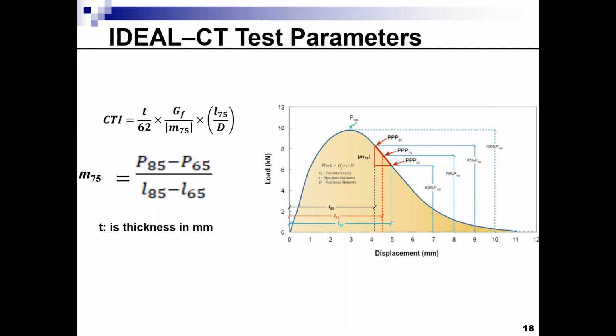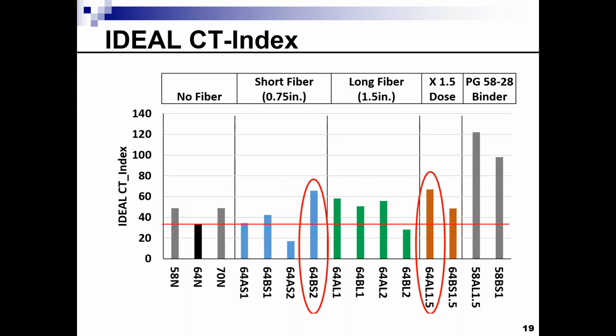We did the IDEAL-CT, and the main parameter there was the CTindex, which I'm showing here. Again, it is based on the fracture energy and also the slope of the post-peak, but there is a different way of getting the post-peak slope, as you can see. You can get it from this equation. So the IDEAL-CT, or CTindex, is another cracking index that has been proposed to evaluate the cracking resistance of asphalt mixes.